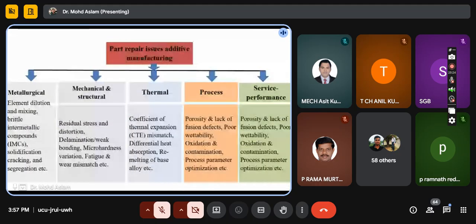So what are the part repairing issues in additive manufacturing? Different types of issues are there. In the metallurgical case: element dilution and mixing, brittle intermetallic compounds, and also solidification cracking and segregation. In mechanical and structural issues, we have observed residual stress, distortion, delamination, weak bonding, microhardness variation, fatigue, and mismatch.